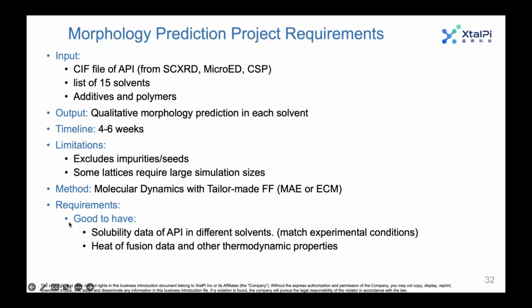And then some other requirements that are good to have but not necessary for the project, things like solubility data. That way we can set up the predictions under the experimental conditions. If not, we can just use a moderate supersaturation for the calculations. Also, thermodynamic data like heat of fusion can benefit the force field fitting procedure, but it's not necessary to get good results. For example, for the metformin project, we didn't use any thermodynamic data in the fitting.